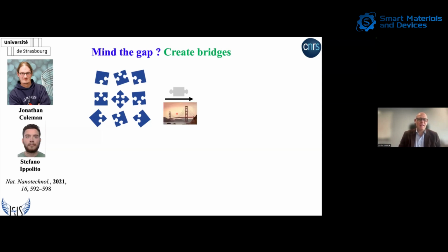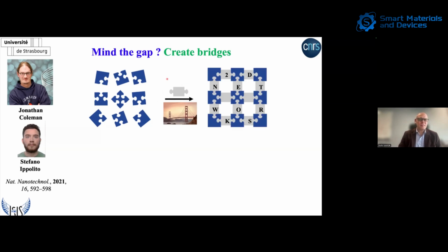What I thought is that here we could help him with a bit of chemistry. The idea is that molybdenum disulfide nanosheets that you disperse on a surface can be seen like pieces of a puzzle that are disconnected. So you can choose the complementary piece of the puzzle that acts as a bridge and connects them, creating a network. If you want to see this from the chemistry perspective, these are the nanosheets that can be molybdenum disulfide, but we also proved this with rhenium disulfide and tungsten disulfide.